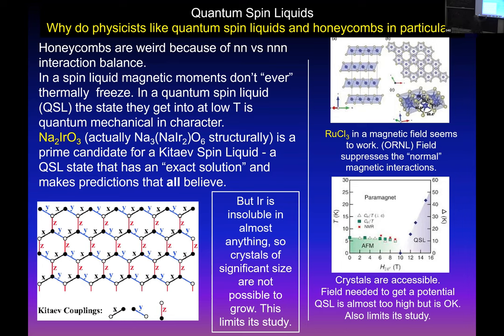So ruthenium trichloride, which I showed you crystals of before, seems to have a regular magnetic ordering at low temperature, but when you put a magnetic field on it, you can make the regular ordering go away. At 8 tesla, or 10 tesla, which is 10 times 10 to the fourth oersteds, the Earth's field is half an oersted, right? You can change the interactions between the magnetic moments so that it becomes something and nobody knows what it is. They think it's a quantum spin liquid. So the good news is ruthenium trichloride is the first one to do that. The bad news is the field is really high.